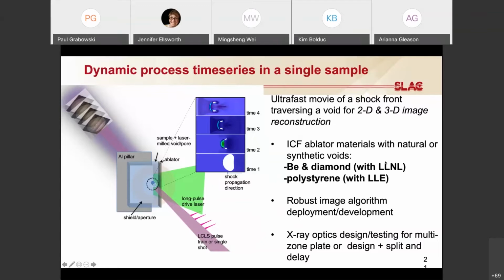So our focus here is an ICF ablator study, and we're working with colleagues at Livermore for beryllium. We've not yet completed any of the beryllium shots. We've got a secondary containment protocol that we're developing here at SLAC in order to do that. Diamond, we've coordinated with Livermore and GA for diamond ablators, and then polystyrene in consultation with Livermore colleagues as well as samples directly from LLE.